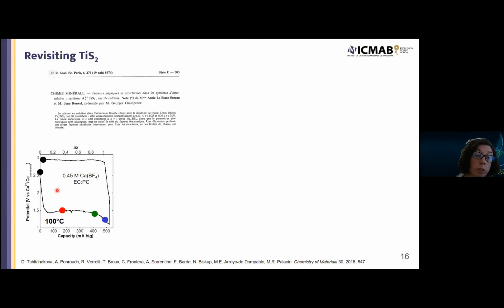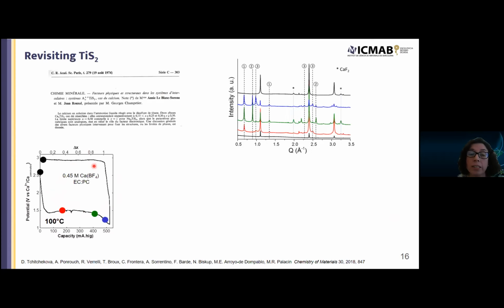There seems to be a reversible behavior, but the polarization is huge, so really not of practical interest. When we did the diffraction ex situ at different points, this is what we see. There is always a significant amount of TiS2 which has not reacted, so there is likely an issue with kinetics despite 100 degrees C. But we see the formation of different phases, as you can deduce from those peaks at low angles in diffraction.